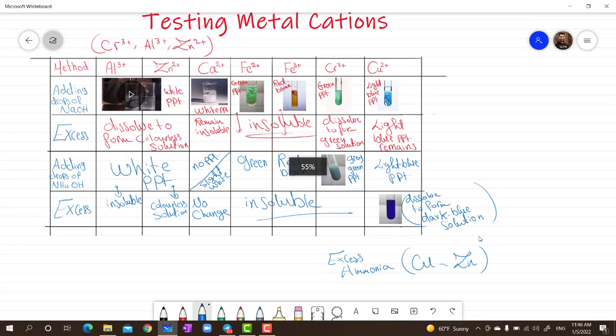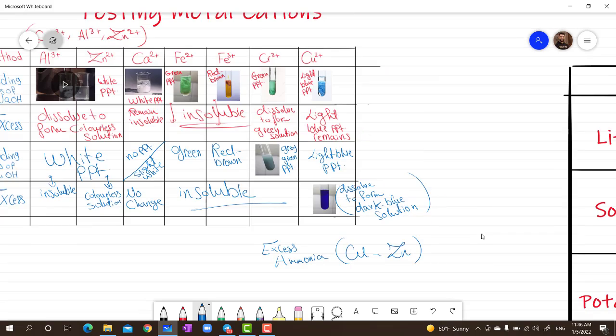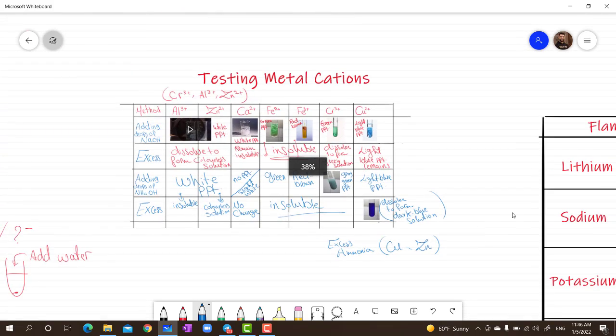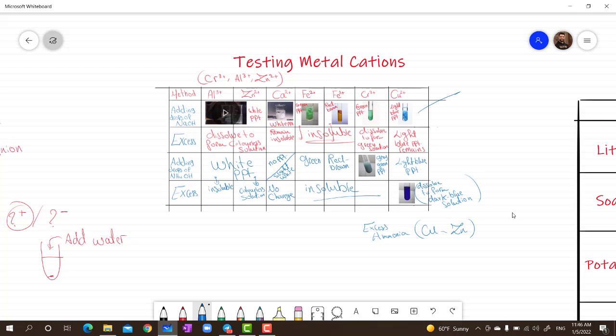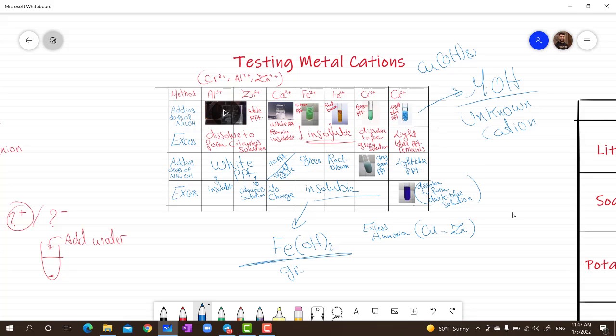Now, there are some cations that we cannot test using this procedure, because their hydroxides are soluble in water. Because these precipitates that we wrote their colors are the metal hydroxides of the unknown cation. For example, the light blue precipitate of copper is copper hydroxide precipitate. The green precipitate of the iron is iron hydroxide precipitate. And we have to mention that the iron hydroxide precipitate, which is green, if left for some minutes, will be oxidized to iron 3 hydroxide, which is red-brown. So there is a color change from green to red-brown.